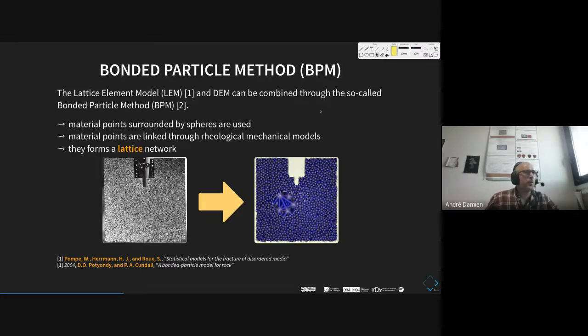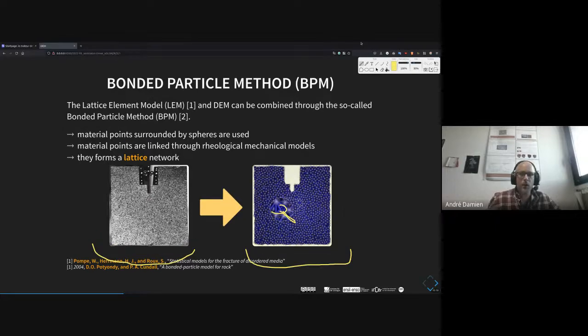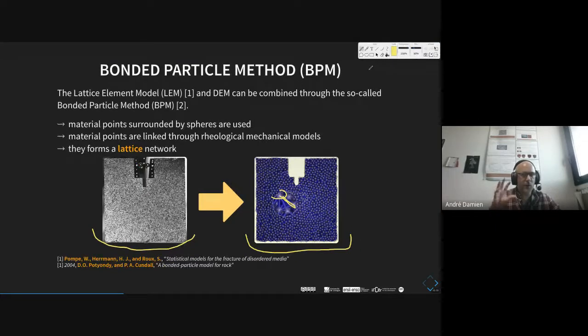So here this is the real experiment, and here this is the discrete element model, where you can see some discrete elements which are linked by what we call bonds, and these bonds are rheological mechanical interactions between discrete elements. So with this kind of trick, in fact, we can simulate a kind of continuous material only with a discrete description.